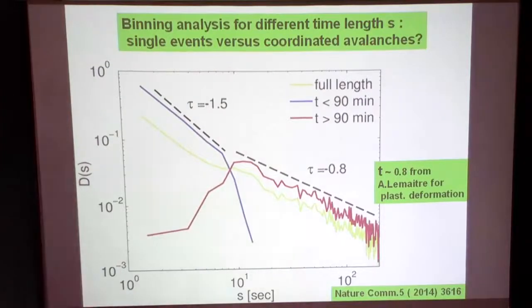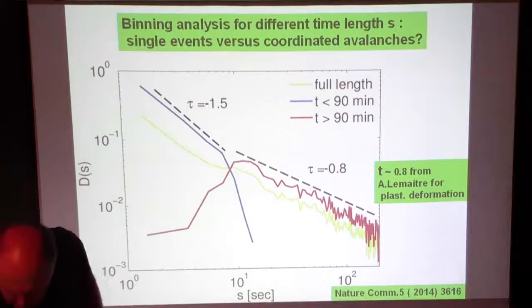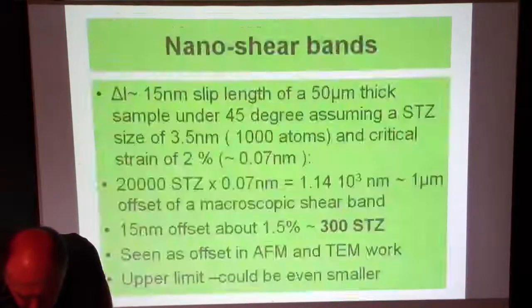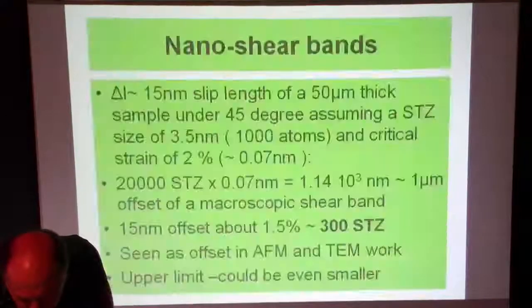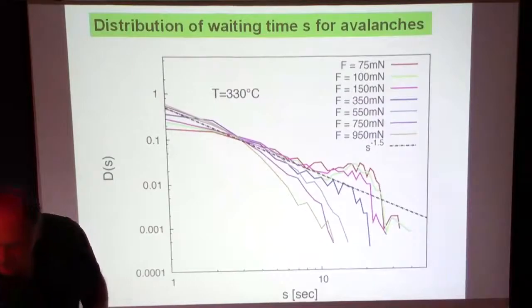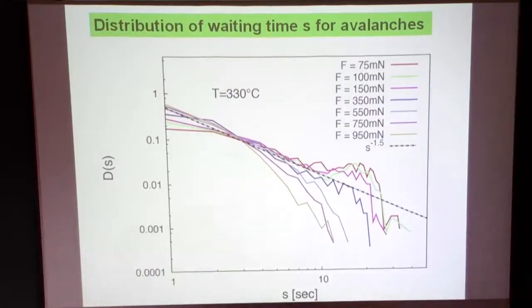So you have an applied stress, right? Yes. Fixed. And if you make the stress lower? Then we see the avalanches the way I showed before. Oops, the wrong direction. We see only those. If we go down in temperature, if we go down in stresses, well, not stresses, but down in temperature, we see that they cut off.